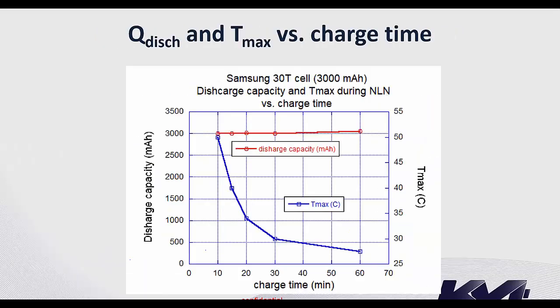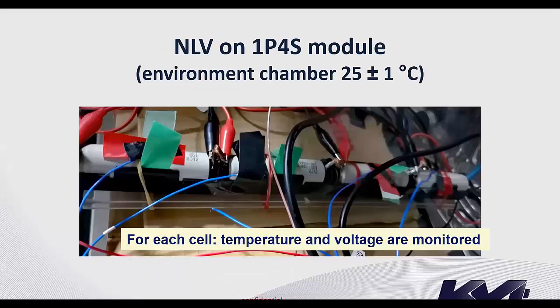Okay, the interesting thing is that whatever the charging time on the x-axis here, from 60 minutes to 10 minutes, the capacity of the cell hasn't changed. It's always 3000 milliampere hours, okay? That's very important. We are really charging the battery 100%. That's very good news, okay? And the other thing is that this NLV technique can also apply to batteries assembled in series and in parallel.